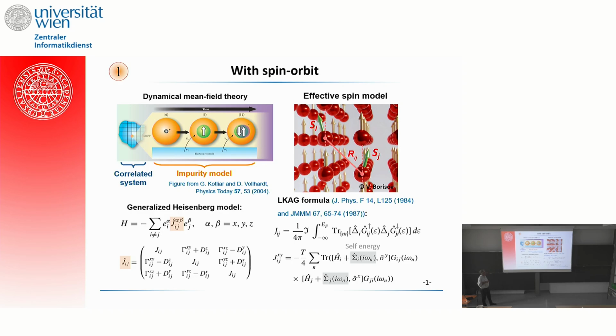So the fact that it's spin-orbit that drives these off-diagonal components, maybe intuitively you can think about it that it's spin-orbit that couples the spins to an underlying lattice. That's how the system knows that there are orientational preferences that would drive these off-diagonal components. Typically, these are much smaller than the diagonal ones. So Heisenberg typically dominates. But in some cases, the DM interaction can be of the order of 10% of the J's.